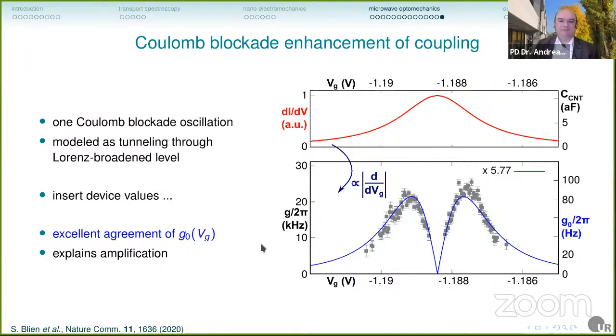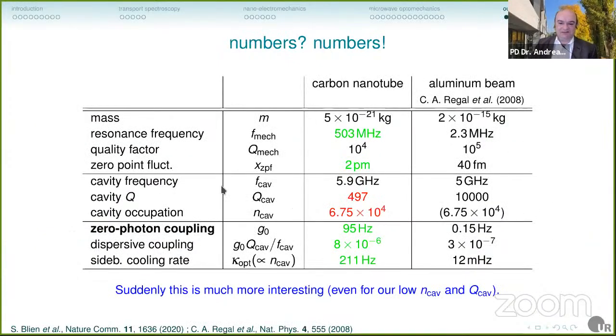Yeah, and now this suddenly becomes much more interesting. Why does it become much more interesting? Well, first, let's look at this table here again. We filled in the new values, and now our coupling is much stronger than even for the aluminum beam. Zero photon coupling, dispersive coupling, the sideband cooling rate, and there's a lot more of these characteristic numbers for optomechanical systems, and they are all rather large. And this is much more interesting because now we are reaching parameter regions where interesting physics happens.